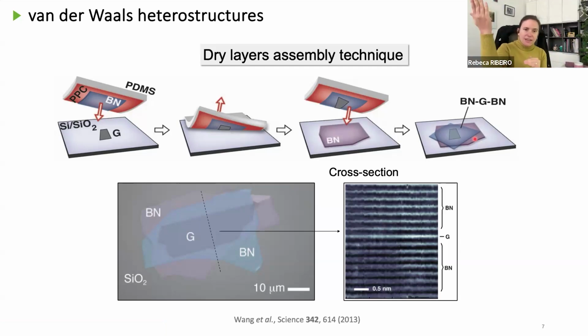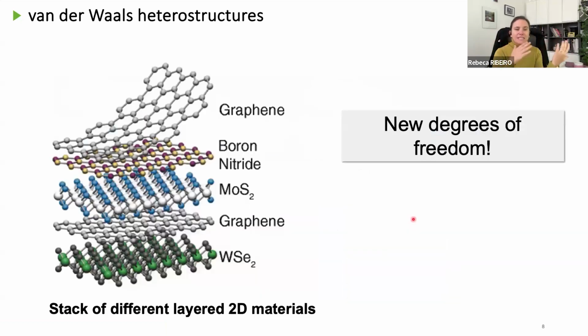So putting layers on top of each other not only gives you the possibility of encapsulating materials, but also of mixing different materials to share their properties. Like, for example, inducing a spin-orbit coupling in graphene when you put it in proximity with a material with a strong spin-orbit coupling. You can also change the conduction of graphene, change the doping of graphene. And these new degrees of freedom that were not available before with, for example, more conventional structures such as gallium arsenide, aluminum gallium arsenide, are very new and completely related to van der Waals heterostructures.